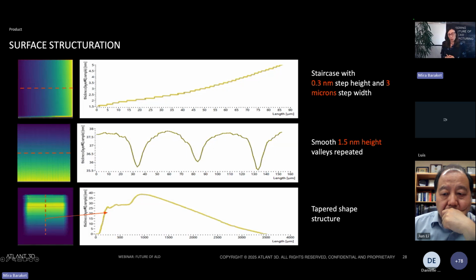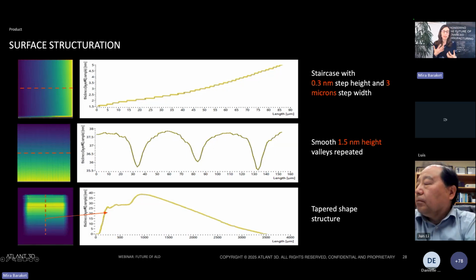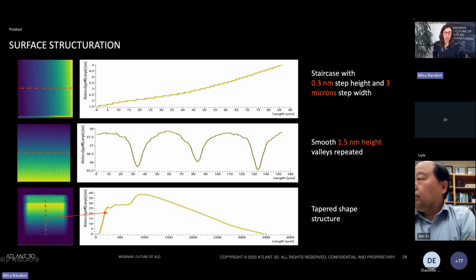So what does it mean? What it means also, if we are able to directly pattern on a surface, is that not only can you create a device with multi-materials, but you also have a new way of surface structuration. Here is an example of 3 different types of structures that are created because of the direct deposition method or direct processing, either by deposition or etching, and I will talk about that in a bit. On the top here, it's a staircase that has been created with 0.3 nanometer step height and with a 3 micron step width. In the middle, these are a few valleys that have been repeated with 1.5 nanometer of height.